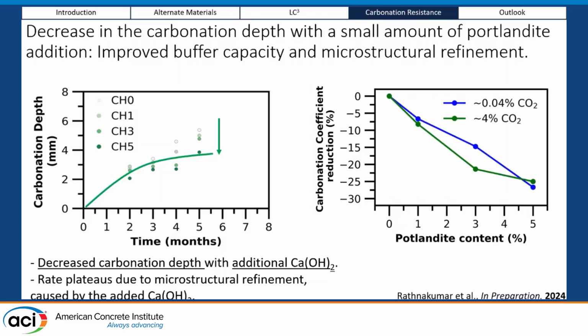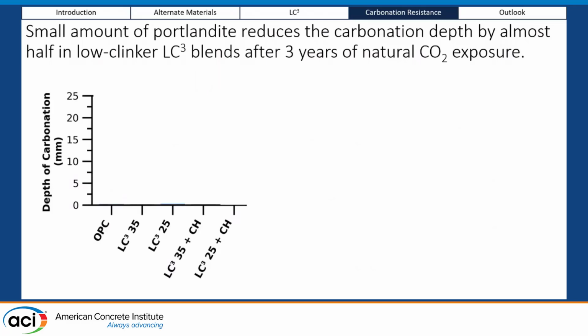Now we see a curve that shows the decrease in the carbonation coefficient as you increase the portlandite content, comparing natural and accelerated carbonation. We see a correlation which is similar to natural carbonation, but about 30% reduction in the carbonation rate, which is caused by the decreased depth. Now, this data is about 3 years of natural carbonation, so really long-term data, compared to OPC.